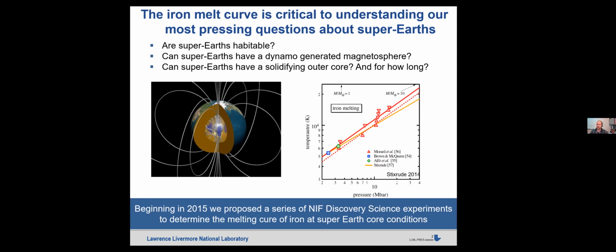And so, of course, when you think about, can they have a solidifying iron outer core, you sort of ask, what information do we have about iron at such extreme conditions? So this is a summary figure from Lars Stixrude's 2015 paper on the melting of super Earths, where on the left axis, we have temperature in a log scale from 3,000 degrees up to 25,000 degrees. And on the bottom axis, we have pressure in megabar from 2 megabar or 200 GPa up to 40 megabar